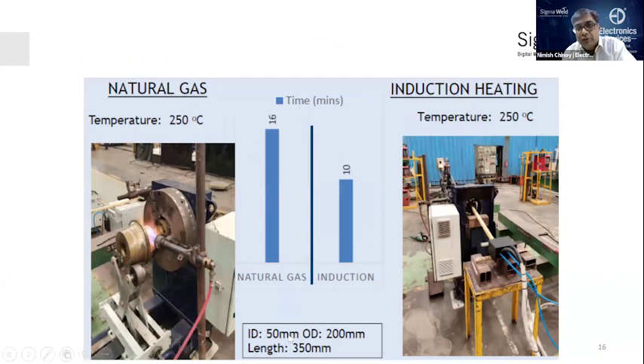Same goes for even thicker vessel. This is about 150 thick, that is 50 ID, 200 OD, and a length of about 350 millimeters. This was a typical setup done by gas burner. It would take about 16 minutes before they could start welding. And here we could do it in about 10 minutes. Again, the coil going from inside and preheating.